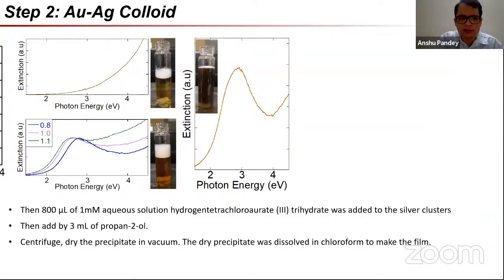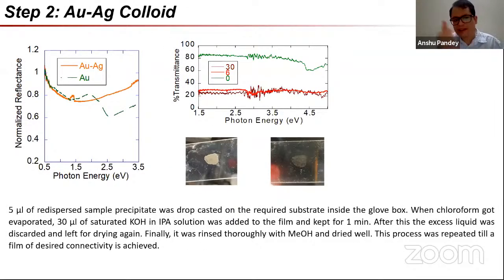Now following that, we are adding gold and subsequently adding the alcohol to destabilize this. So at this stage, the CTAB is partially weakened. There is less and less formation of tighter micelles; rather the CTAB structure becomes loose. So things aggregate partially, but not quite. This is still very darkly colored as a solution. It's very lossy. And now this is centrifuged out of solution, so you collect the black particles. These are then redispersed into chloroform, and that is taken to the glove box.